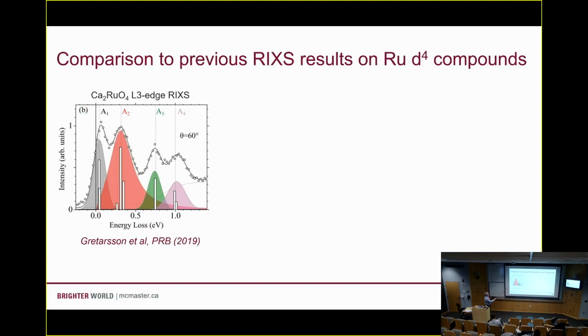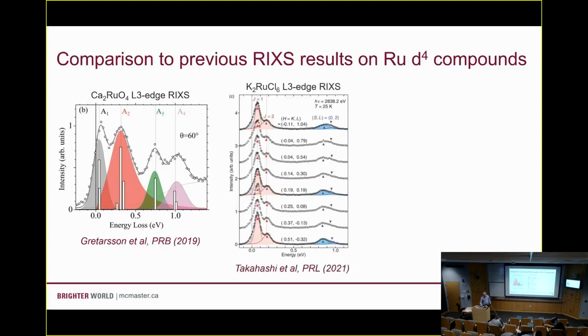Okay? So quick digression here. I mentioned the calcium ruthenium oxide before. These are L3 edge RIXS measurements that were done. You can see the peaks are pretty broad here. That's just a side effect of the coarser energy resolution you get at these ruthenium L edges. Okay. Potassium ruthenium chloride, the antifluorite that we mentioned before. This is a spectrum that looks qualitatively similar to ours. You've got a feature here,